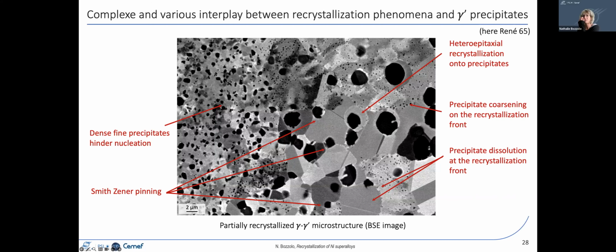There are many small precipitates in there, and these precipitates have prevented the substructures from evolving into recrystallization nuclei. So these grains recover and do not recrystallize because of the dense precipitation state. At other places, we can retrieve the Smith-Zener pinning we have spoken of before, and between two recrystallized grains, you have here a boundary which has stopped at the second phase particles. This is very easy, classical. This is what we have seen before.